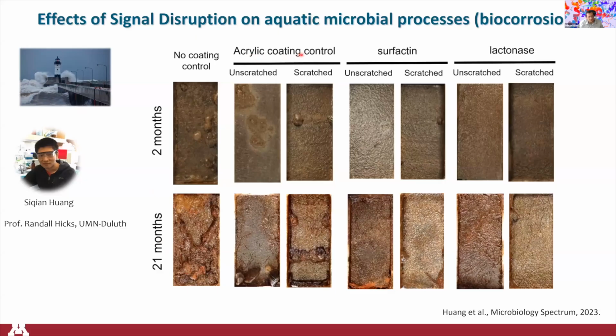And then you have the acrylic coating control. So this is the coating alone. You have quite a bit of corrosion after 21 months, quite a bit of macrofouling as well, with some mussels there. Then you have the surfactin treatment. So this is a biocide that we used as a positive control.